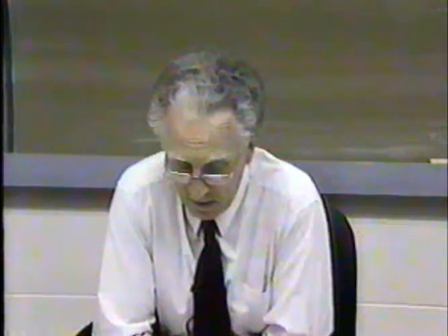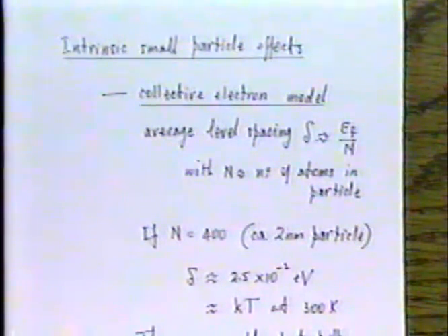In other words, if you ask what is the average spacing between the quantum levels of the electrons in a metallic crystal, it's of the order of the Fermi energy divided by the total number of atoms or electrons present. And that, of course, results in general in the average level spacing being extremely small. The fact that the average level spacing is very small means that metals are conductors at room temperature, because the electrons can be promoted thermally, or something equivalent to that.